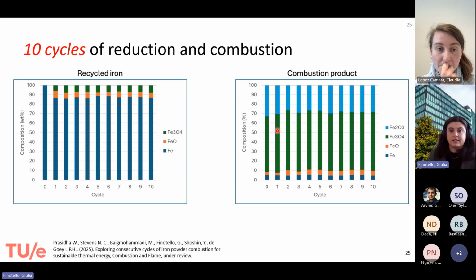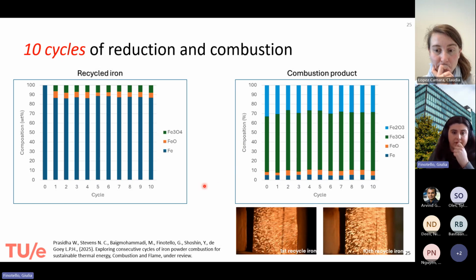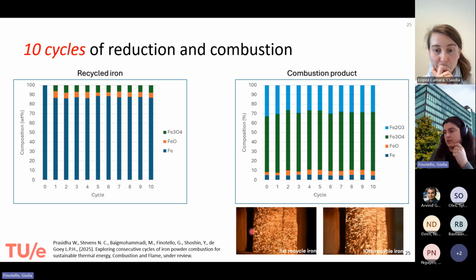We didn't stop here. We also did 10 cycles in a follow-up study. And here you can see the composition for both the recycled, so the reduced iron, and the combustion product. We were mostly interested here in the stability of the different cycles. You can see that we could maintain a certain conversion, so a certain iron composition in our reduced iron, and the same we can say for the combustion product. So we don't observe any large difference in the composition from cycle to cycle. The same is true for the stability of the flame, for example, from the first cycle to the 10th cycle.